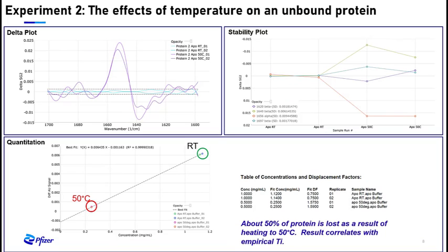On this next slide, we have additional data from this experiment. The delta plot in the upper left-hand corner is generated from the second derivative plot seen in the earlier slide. Holding the room temperature sample at 0, you can observe the peak-to-peak changes in the sample. Here we are looking at the 50-degree centigrade sample. In this plot, the major peak at 1656 indicates a loss of alpha helicity, while the negative peak at 1638 denotes an increase in beta sheet content.